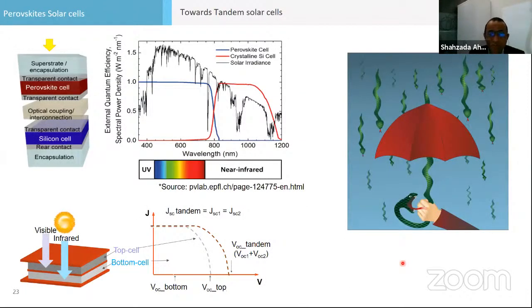The good thing about these emerging photovoltaics is that they absorb in the visible part of the spectrum, from 400 to 800 nanometers. This allows you to think about a tandem configuration, since silicon absorbs in the NIR, from 900 nanometers onwards. So the visible light can be harvested by the top cell, which can be a perovskite solar cell, or you can also use organic photovoltaics. And the infrared light goes through to the silicon solar cell. In this way, you can boost the efficiency. Single junction is here, and with tandem you can boost the efficiency further.